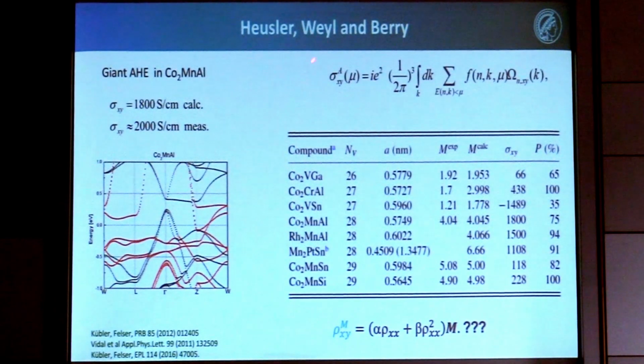So you know Heusler, Weyl, the crossing. So the anomalous Hall effect is a function of the Berry curvature. And this was a little bit contradicting what people did in spintronics for a long time. They always had the assumption that the anomalous Hall resistance scales with magnetization. Now you can imagine, if you simply look at the number of valence electrons and here you see the anomalous Hall effect, it should go linear like Tc and everything. But it is not the case, because it goes really with the Berry curvature. So it looks like the Heuslers are really nice systems where the Berry curvature counts more than extrinsic effects.